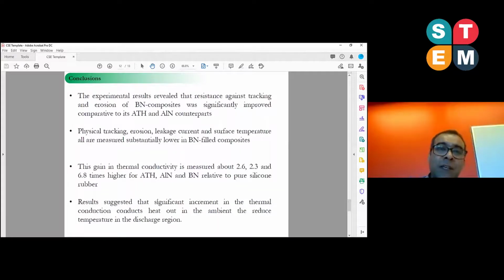So the conclusion is the experimental results revealed that the resistance against tracking and erosion of the BN composite was significantly improved comparative to ATH and ALN. Physical tracking, erosion, and the leakage current and the surface temperature all are measured significantly lower in the BN boron nitride filled silicone rubber samples.